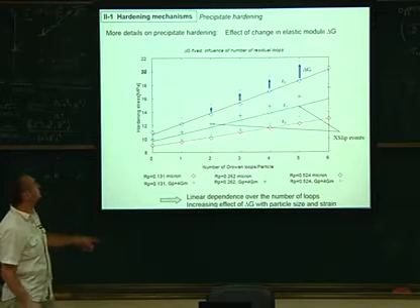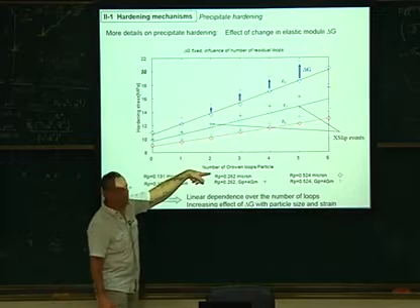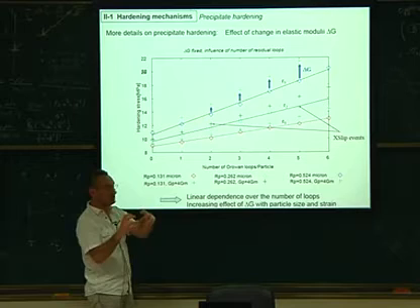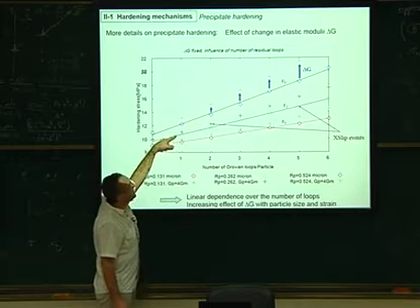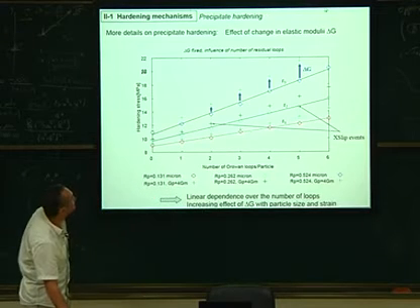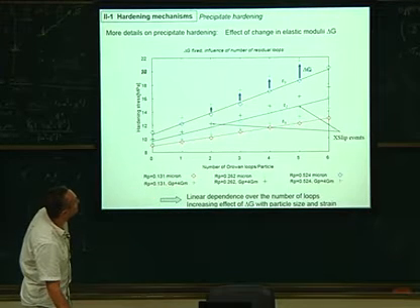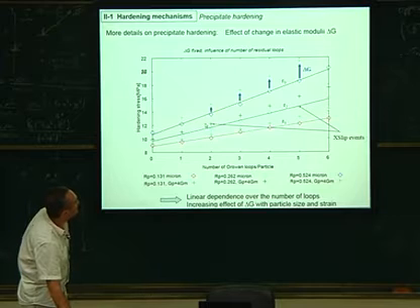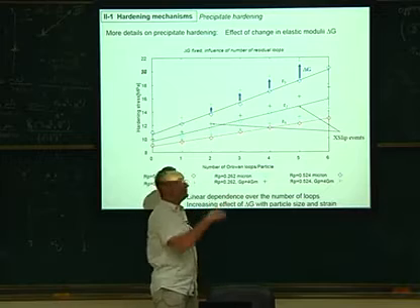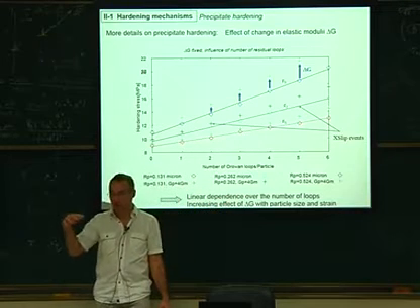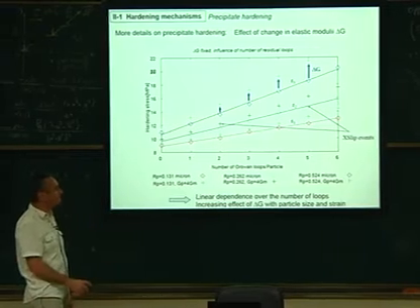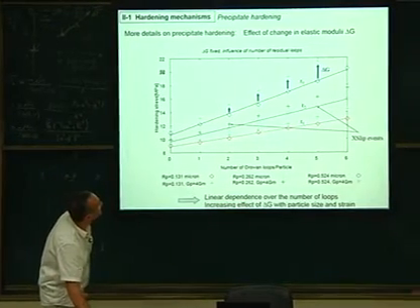So we can plot some curves. We can plot the hardening stress versus the number of loops, just to show the effect of the first mechanism I told you about. So the number of loops which are deposited and this coalescence of the stress field. And this for different sizes of the particles, and increasing the difference in modulus. So delta G is the difference in shear modulus, like this. And what happens is that at this stage or that stage, we found some cross-slip mechanisms that were active, that could escape the particles. Because of cross-slip, dislocations are able to escape and not stay there. The Orowan loops are just removed by cross-slipping. So this is the effect of the change of elastic moduli.